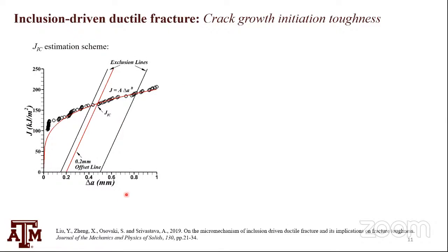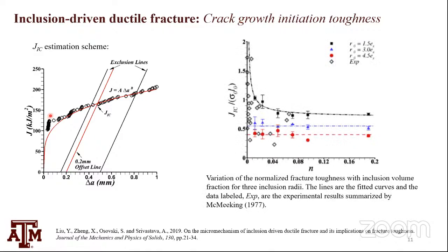So then I can take the J-delta A curve, mimic an ASTM standard where I fit a power law and draw a line, get an offset. That gives me the crack growth initiation toughness, which is the J1C value. I can plot this data with microstructure parameters. So I can now correlate crack growth initiation toughness with volume fraction of inclusion and size of inclusion.